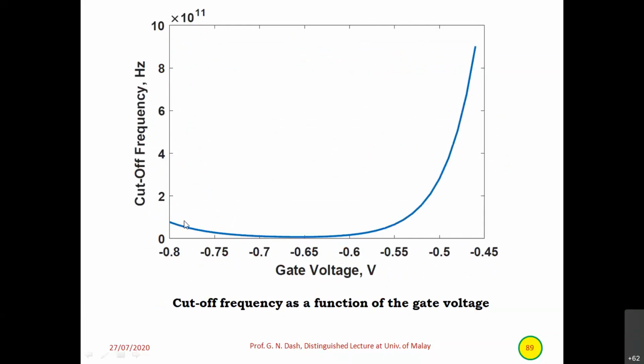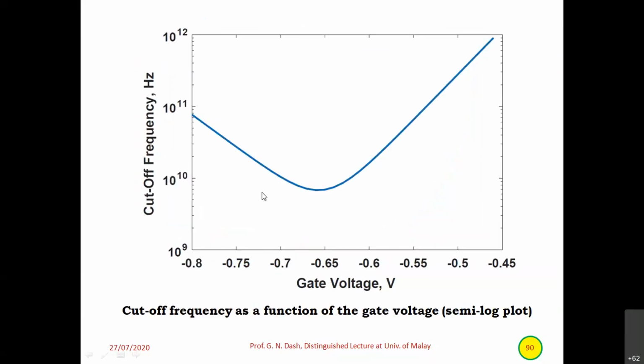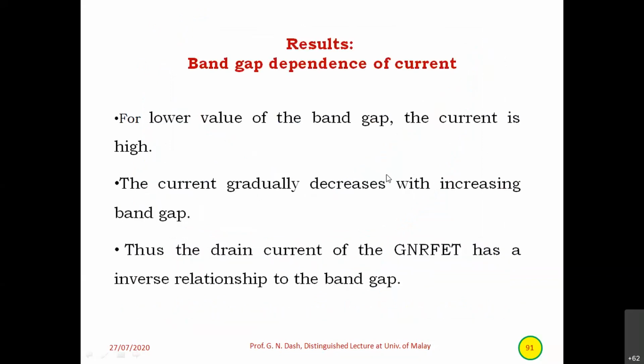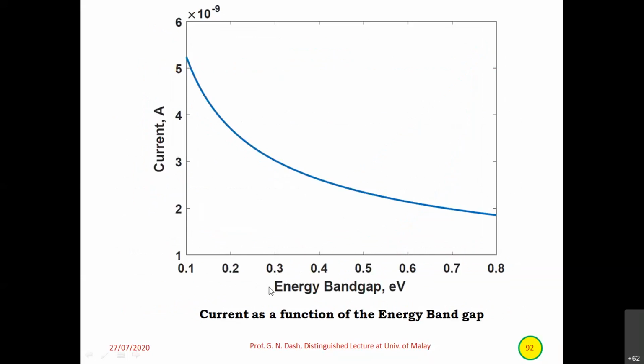Cutoff frequency, you can see this is a normal plot of cutoff frequency. We get a minimum at 0.65, and then it increases. If you take a semi-log plot of the cutoff frequency, you get a clear minimum here. Then the band gap dependence of current. This is a standard relation. The energy band gap can be changed only by changing the width of the graphene nanoribbon. If the width of the graphene nanoribbon is varied, then correspondingly the energy band gap can be determined. As a function of energy band gap, when the energy band gap decreases, the current increases. So this is a standard relation.